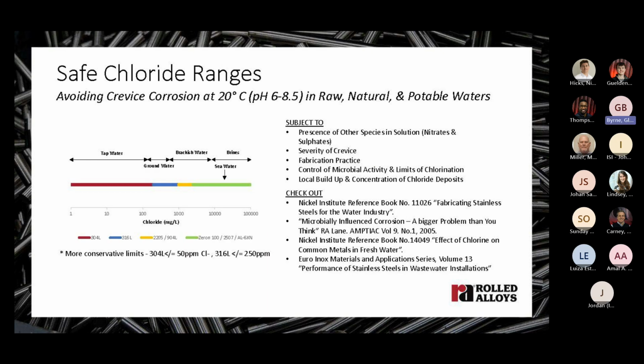In this next slide, I show the generally accepted safe use limits of chloride for these alloys of interest. These are considered to be good rule of thumb figures. 304L, for example, the red line, is good up to about 200 ppm chloride, but for performance between 200 ppm chloride and 1000 ppm chloride is limited. 316 is good from 200 ppm to 1000 ppm chloride, as you see here. And 2205 and 904L is good from 1000 ppm chloride to about 3600 ppm chloride. Above this limit, you rely on 6% molybdenum superaustenitic stainless steels and 25% chrome super duplex stainless steels.